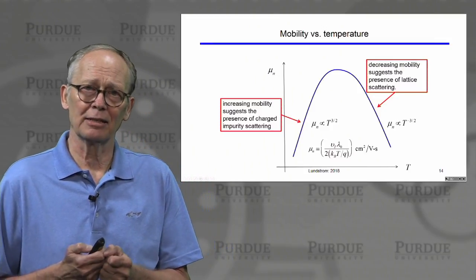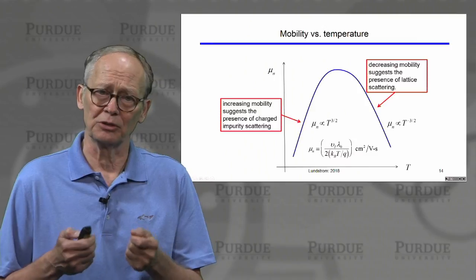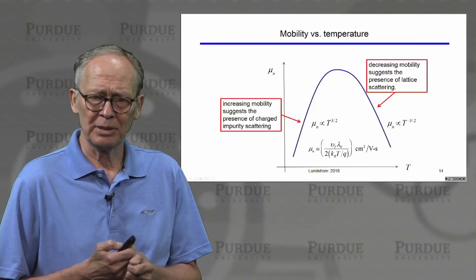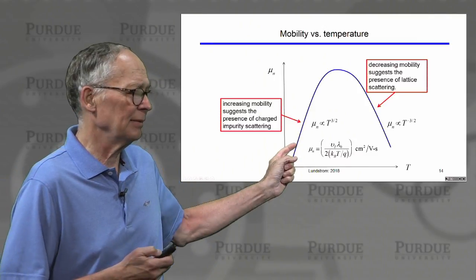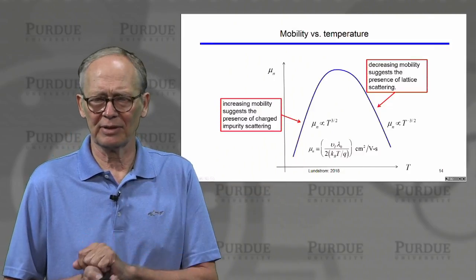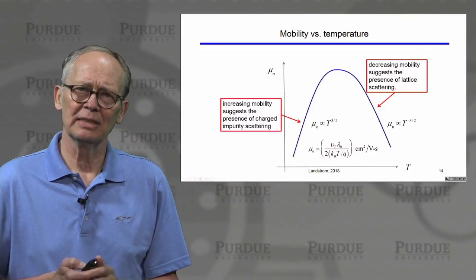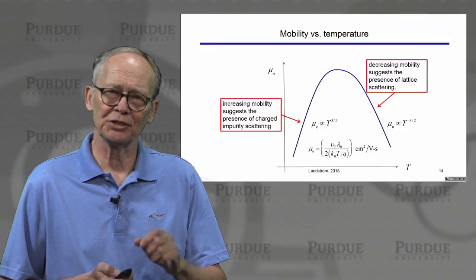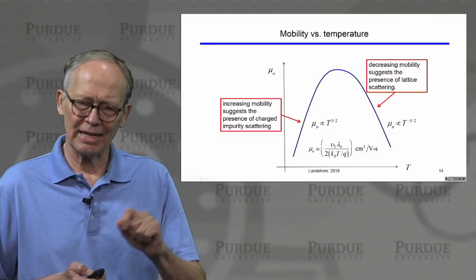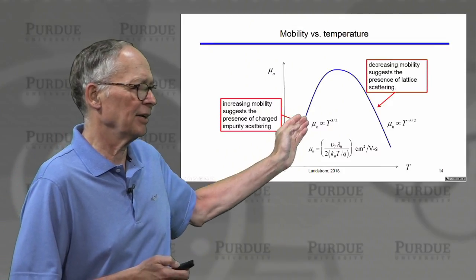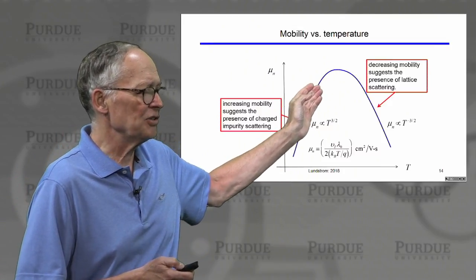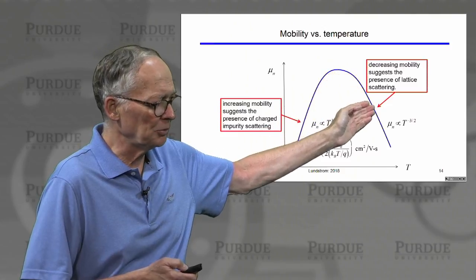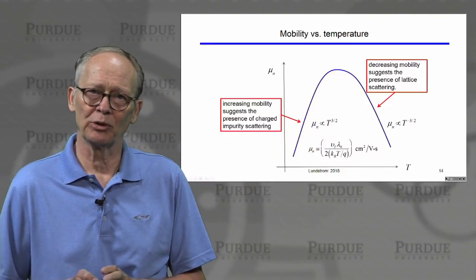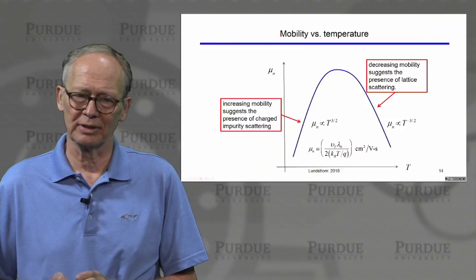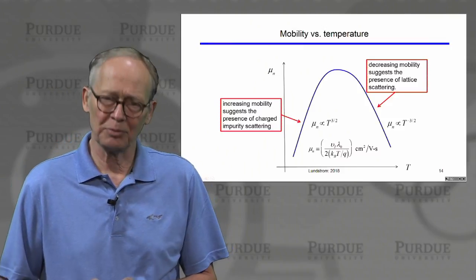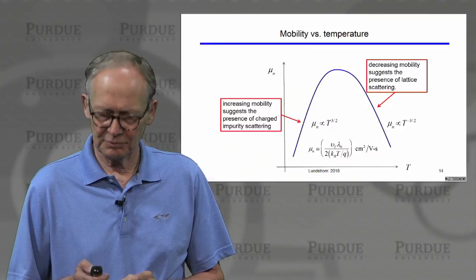The scattering is likely to be dominated by the interactions with the dopants in the semiconductor lattice. But there, as I increase the temperature, I increase the average thermal velocity. So electrons zip past these charged ionized impurities faster. They interact less, they're scattered less, so the mobility gets higher as you increase the temperature. Eventually, it turns around and drops as the lattice scattering gets more and more important and starts to take over and lower the mobility. So you'll see these characteristic curves that are frequently measured.